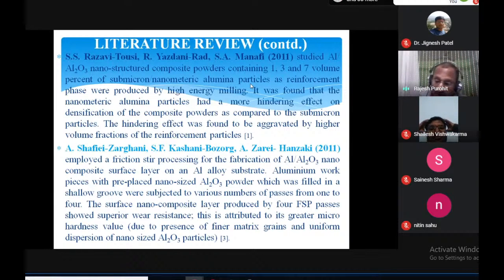So the FSP process is basically also used for fabricating surface composites. On the top surface we can mix the nanoparticles or micron particles, but inside it remains ductile. Inside, particles are not mixed. Only on the surface do we get mixing of the nanoparticles, by which the upper layer becomes stronger.